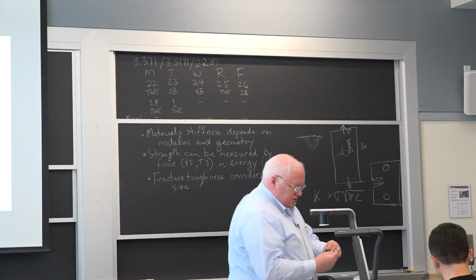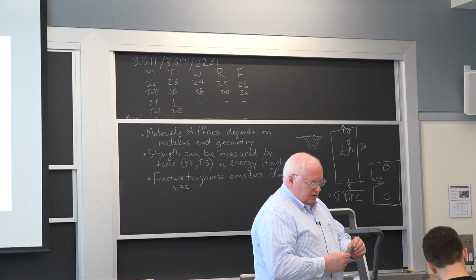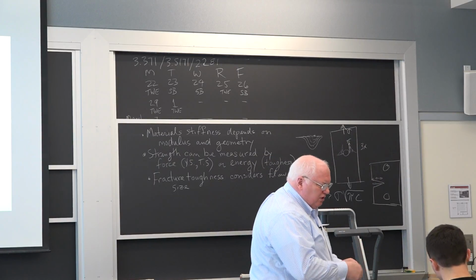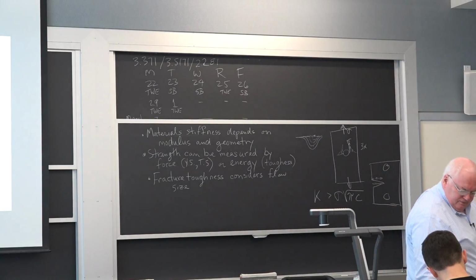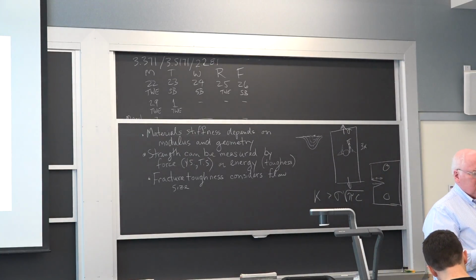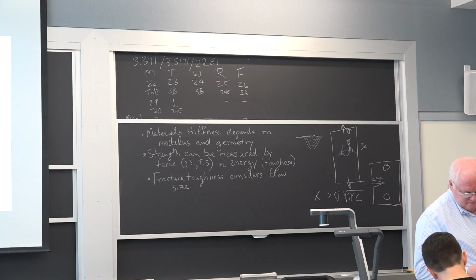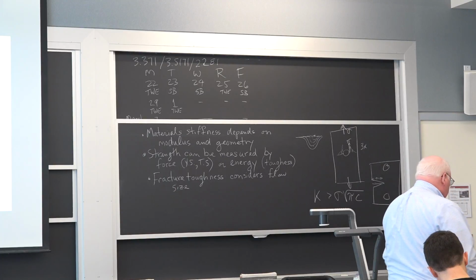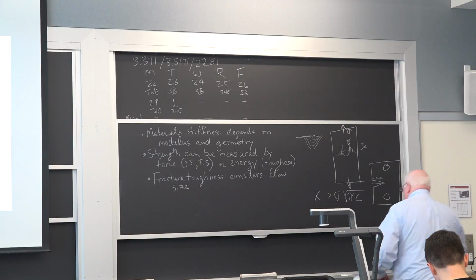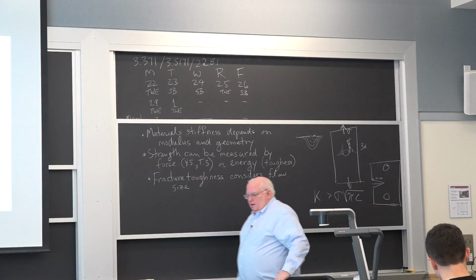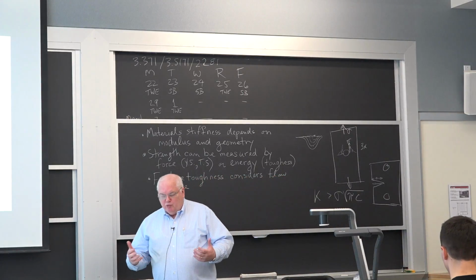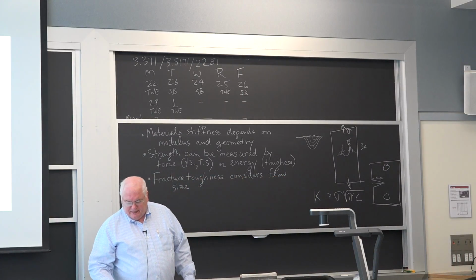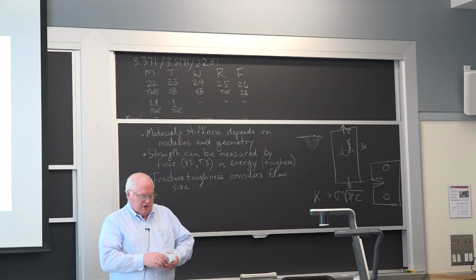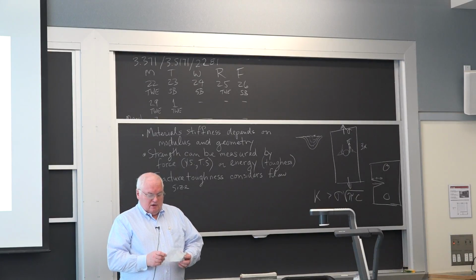If you look on the fracture surface here, you'll see a little shear lip. At least on one of the brittle fractures, you should see a shear lip. Not very big for shear lips on these. Now there's a little one on here. A little 45-degree slant, which was the compression side of the fracture. There was enough stored energy in that even though one of them broke, the other one was close enough to breaking, we still run into brittle fracture today, okay, in all kinds of structures.